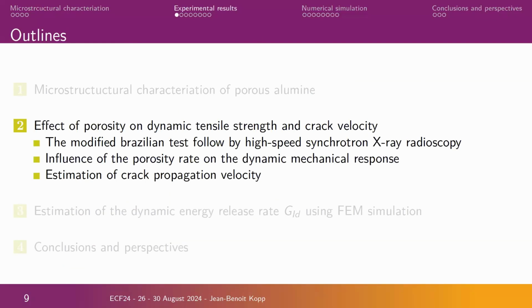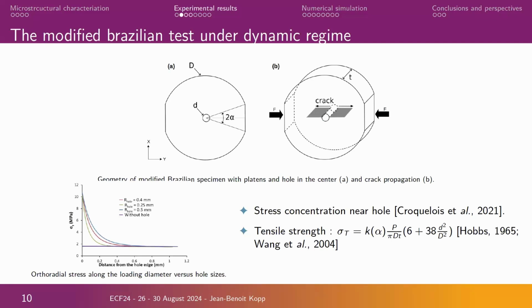So what about now the mechanical behavior in dynamics? As I said before, we use a specific modified Brazilian test geometry with specific flats. Because it's well known for brittle materials that we can have a stress concentration just here during the mechanical loading. So by using this kind of flats, it's well known that we can concentrate the maximum stress near the center of the specimen. But as we worked on porous alumina, by introducing a hole, a specific notch, an artificial defect larger than the pore defects, it was possible to be sure to initiate the crack at the center of the specimen. So finally, it is possible to estimate and calculate the tensile strength by considering a geometrical factor to take into account the specific geometry of this Brazilian test.